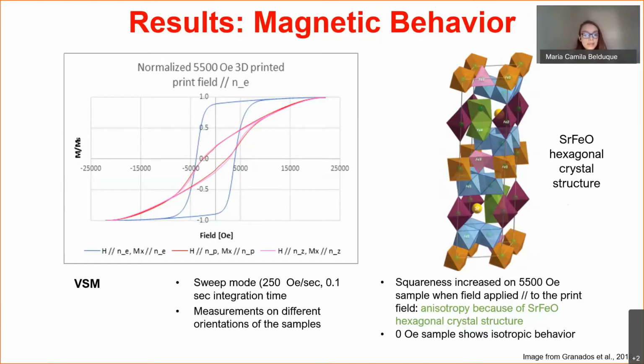In this case, note that the squareness parallel to the field, represented by the blue curve, is largest when the field is applied parallel to the print field direction, which is n sub E. This indicates that the 3D printed material is anisotropic, and the print field induced a magnetic anisotropy in the composite by aligning the easy axis of the individual strontium ferrite particles along the print field direction.